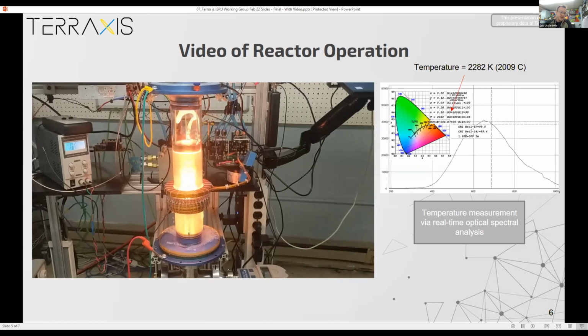So we operate above 2000 C. We've operated for varying lengths of time, from a couple of minutes up to about an hour steady state. And our focus to date has really been on the core power delivery and energy management system, to make sure that we can sustain and hit these critical temperatures needed to separate out the different materials. So the test stand has been going through a lot of different configuration changes, but the core value proposition of hitting these temperatures has already been demonstrated. So next slide.